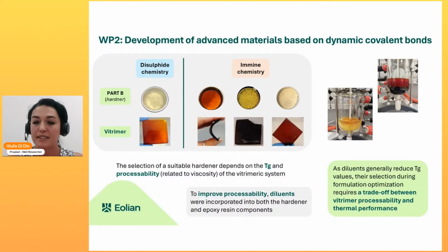To improve this processability, diluents were incorporated into both the hardener and the epoxy resin components. However, these diluents often reduce the Tg values. So one of the main cores of this research study was the formulation optimization, to find a trade-off between the vitrimer processability and the thermal performance, which must be in accordance with the requirements of the project.